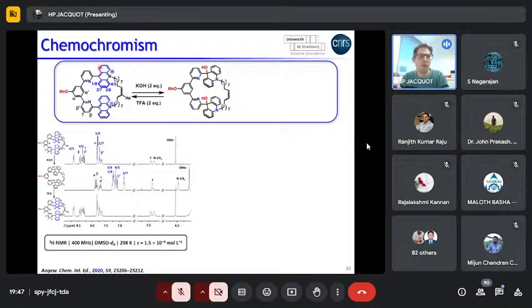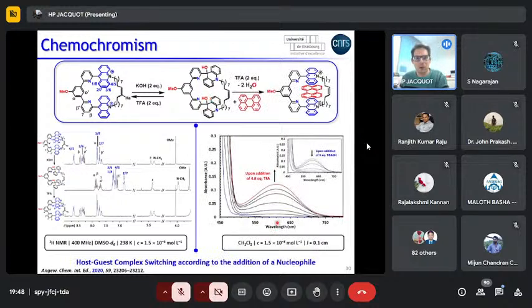Why? Because first of all, you have a dearomatization of the acridinium cores, a loss of their positive charge. So basically this motif is more like a diarylamine, which is an electron-rich building block and does not want to interact with perylene. And also, the last thing is that you have a distortion of the cavity of the macrocycle since you have a hybridization change from the C9 atom here, from a carbon sp2 to a carbon sp3. Fortunately, the recognition properties can be fully restored upon addition of trifluoroacetic acid, and this is 100% reversible upon addition of hydroxide ions. So if you want, we have an on-off system for the recognition of perylene.